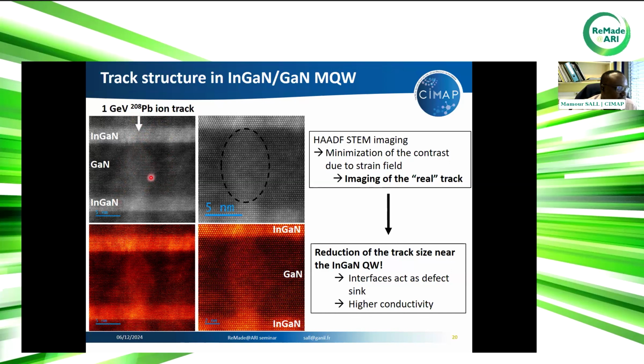It's not really clear in this grayscale image, but it's clearer in this colorized one. These two images are the same: this one is grayscale, this one is colorized. In the colorized image, you can see we have a track here, and the track is bigger inside the gallium nitride layer than when we go near the indium gallium nitride. Once again, this imaging mode, HAADF, is not sensitive to the contrast due to the strain field. So what we observe is really the real track, the modification done by the swift ion in the material.